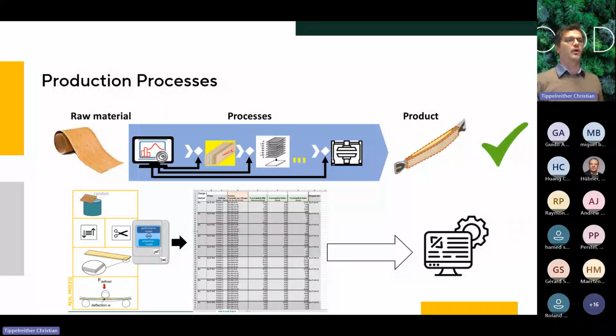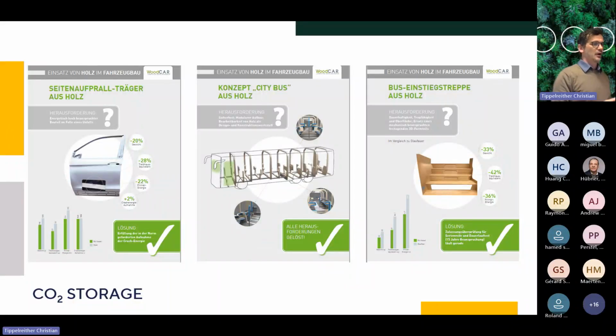With the main benefit, beside some technical benefits we can get with wood, also the benefit regarding CO2 storage. Unfortunately this is not only in German, but you see it in the picture. We have some from the wood car project, the research project, the side impact beam from the car. We have here a bus entrance stair from a bus system. And here we substitute a steel part. In this way, we substitute a glass fiber reinforced part. And you see here on this part, we get less than 20% in weight, and can reduce the CO2 equivalent by up to 30%, and also the primary energy consumption for the production process by up to 22%, while also ensuring the needed stiffness and the needed energy absorption for this part. So we find technical solutions which work.